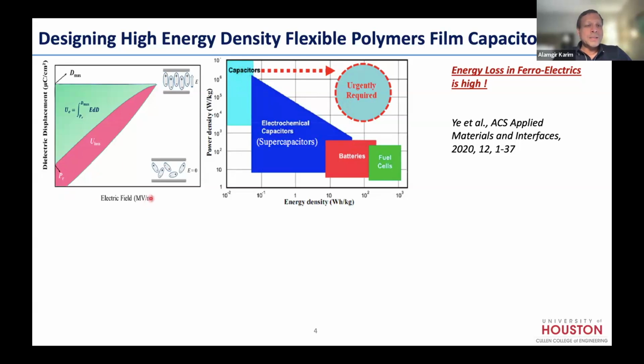So when you charge a capacitor, as shown here, then you discharge it up to the point of breakdown. You see the green area is the energy storage in the capacitor. The red is the loss part. So if you return back to zero field and there's residual displacement in the dipoles that did not fully recover, you have lost this much energy in pink, whereas the green is the energy. So we want to maximize the green region.